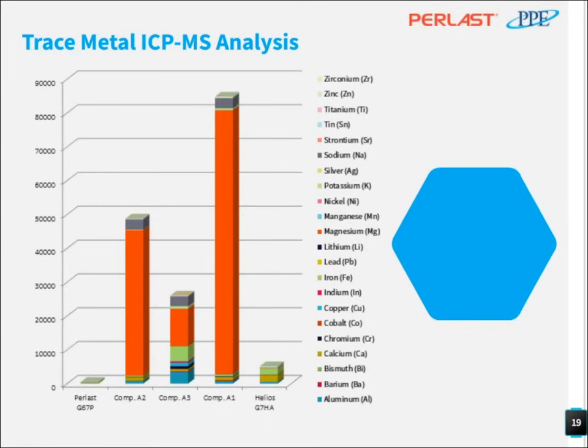So if I give an example about the desired levels of purity for critical applications, for example, where the seals are in very close proximity to the wafers or in direct contact with the wafers, the limit set by big OEMs is usually 10,000 parts per billion. For slightly less critical application, it is 25,000 parts per billion. So as you can see here, the total metal contaminants of PPE materials are extremely low.